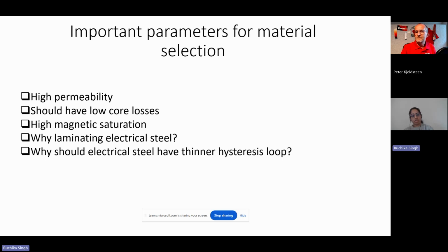In a motor, all you want is to have better torque performance. It's a combination of two parameters: the flux density you can get in the air gap of the machine, and the current you can push through the windings. The combination of these two gives you the torque. So you always optimize for these two parameters, not mainly only these two, but these are the two parameters you play with to produce the torque. Now, if you have a material where you're reaching the magnetic flux density limit fast, or saturating quickly, you'll have to push more current to get the required output from the motor.